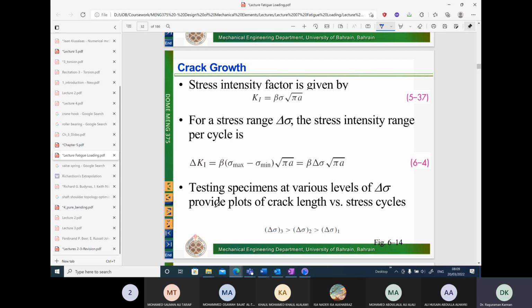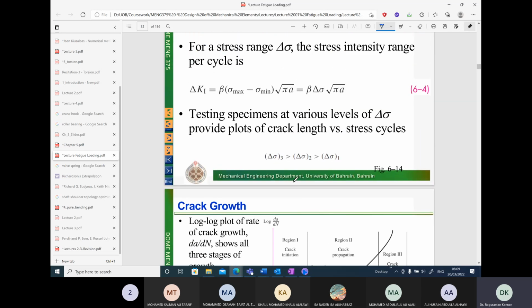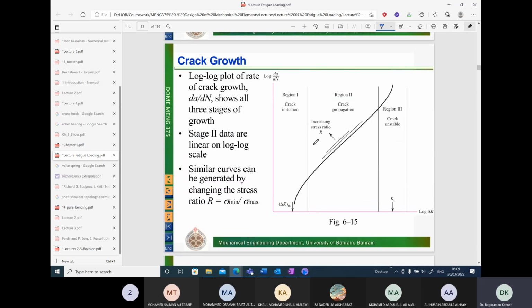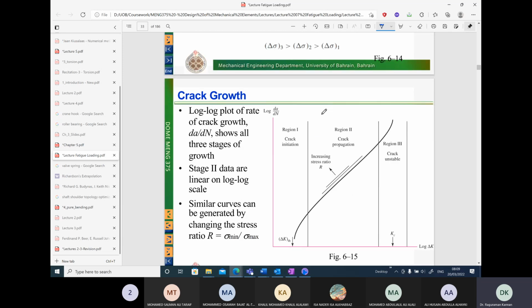Testing specimens at various levels of delta sigma provide plots of crack length versus stress cycles. Okay. So what kind of experiment do we do? We again do experiments with a lot of specimens and for various values of delta sigma. So in this order, we do the experiments and then we obtain the data. Okay, so let's see here for various values of delta sigma, we provide crack length versus stress cycles plot. Okay, once we have this plot, this is a different plot again.